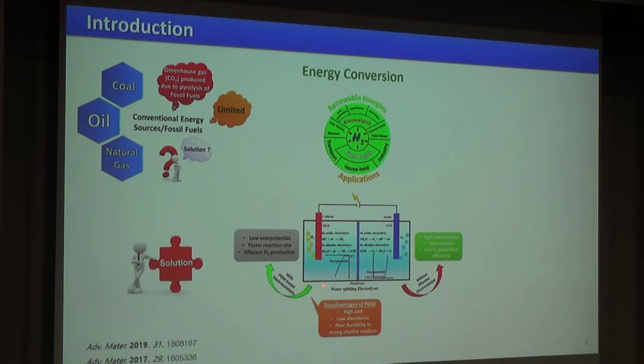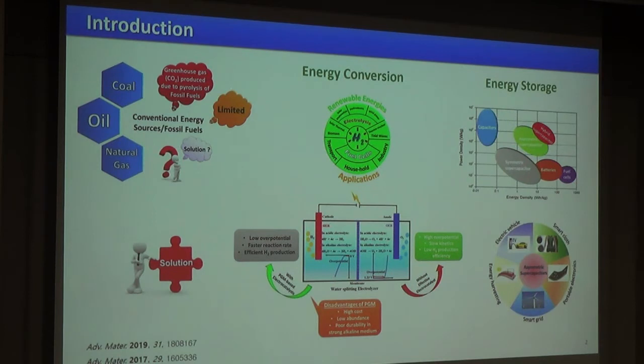Among these two reactions, the anodic OER is a 4 electron transfer process, whereas the hydrogen evolution reaction, or HER, is only a 2 electron transfer process. As a 4 electron transfer process, it is much more complex than the HER. So it is much slower and also associated with a higher overpotential than HER. So this OER process is considered the rate limiting step for the overall hydrogen production efficiency, and we are interested in this part.